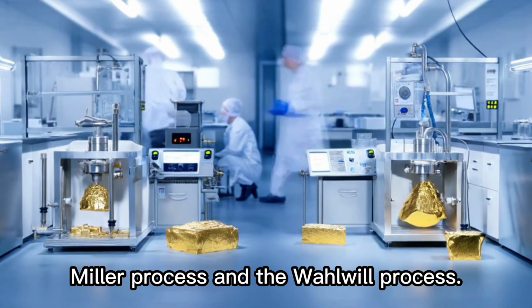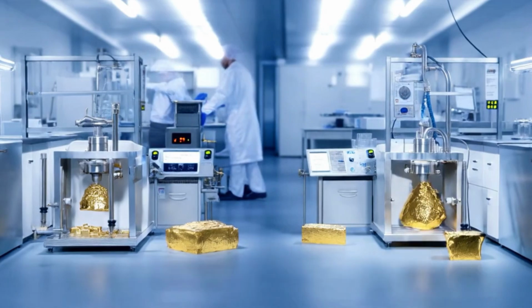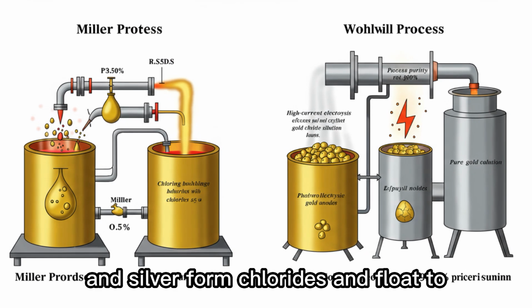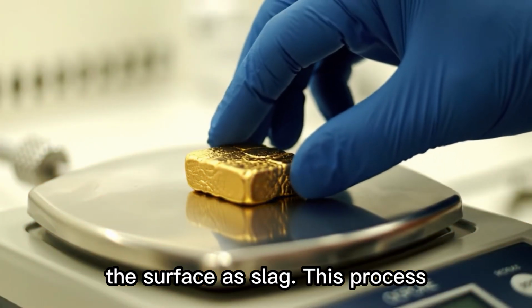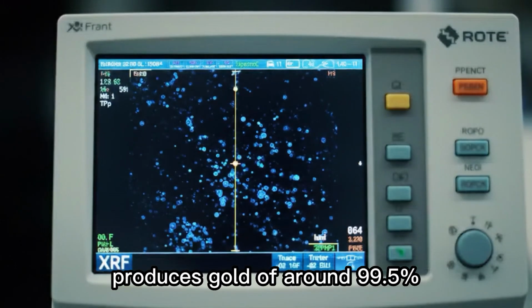6. Refining, the key to 100% pure gold. Doré bars are sent to a refinery where they are further purified. The most widely used methods for refining are the Miller process and the Wohlwill process. In the Miller process, chlorine gas is bubbled through molten gold. Base metals and silver form chlorides and float to the surface as slag. This process produces gold of around 99.5% purity.